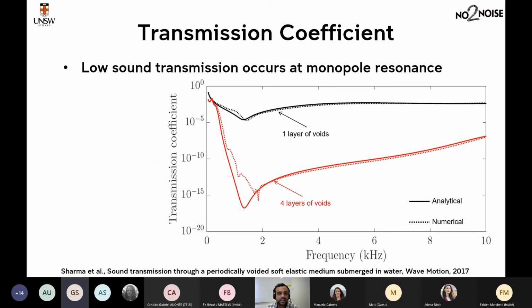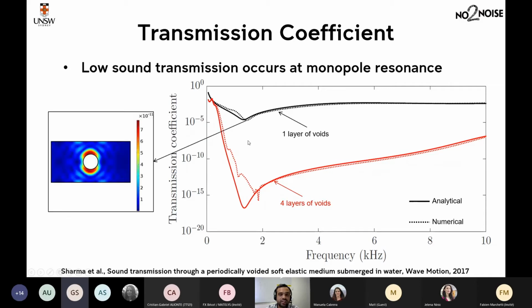So this slide shows the transmission coefficient when you have one layer of voids and four layers of voids in your soft media, obtained analytically as well as numerically, right? You can see that the results are in very close agreement, and there's a trough in the transmission coefficient. This trough corresponds to monopole resonance of the cavity, as you can see in the displacement plot here.